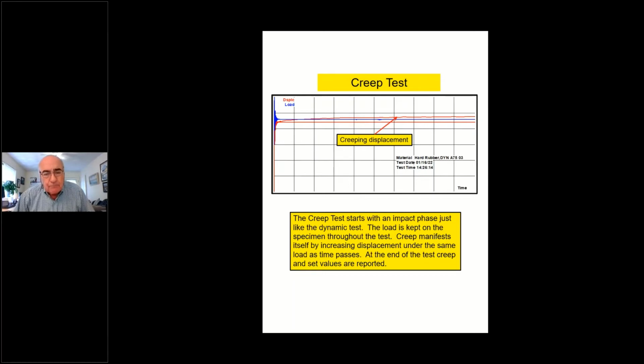We also do that. And it is important to be able to measure creep for various end-use applications, such as O-rings, seals, and for example, if you think of seals and O-rings, certain applications such as sealing nuclear waste encapsulated in tanks or whatever with an O-ring, you don't want that to leak if there's an earthquake or something. Meaning, if there's a danger of leak, the O-ring has to recover within its capability as soon as possible, so the leak will be minimized. And there is the natural frequency characteristics and the dynamic properties come along very importantly.